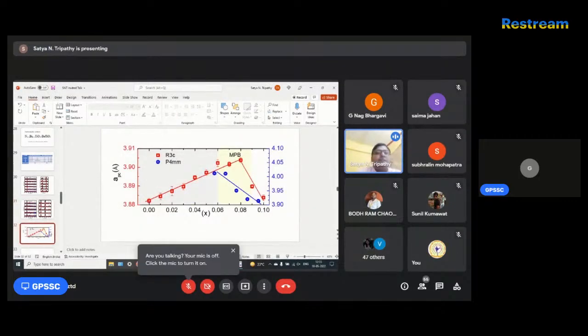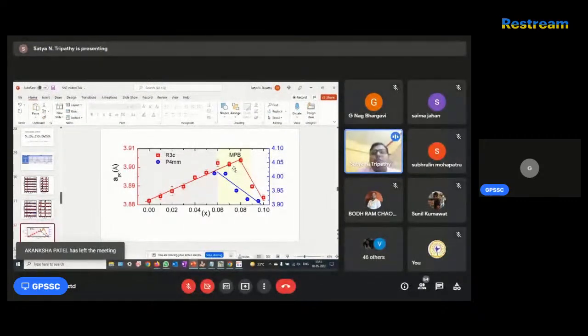So this graph is basically the pseudo-cubic lattice parameter. As I have told you, this lattice parameter is basically the primitive cell volume, and you take a cube root of it. And this is the composition, and you can see up to 0.06 we have the R3C phase, and after that we have a dual phase, and most of the phase appears at 0.08 or 0.07. This is actually the critical stage. So most of the people report 6%, 7%, 8%. Whatever the results we obtain, it is 7%.